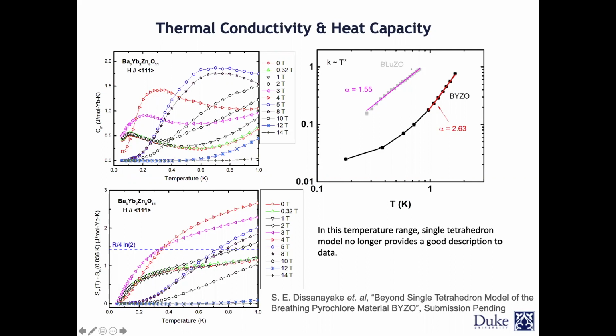And more importantly, if we start to look at the thermal conductivity, for example, this is the thermal conductivity as a function of temperature for barium lutetium zinc oxide. Lutetium is the isostructure of barium ytterbium zinc oxide. However, it is non-magnetic, so whatever it shows should be only due to phonons. And this is actually what we are seeing. If we fit it and check for K proportional to T to the power of alpha, it is more or less what you would expect if somebody only had phonons in it when you start to warm it up, and then the phonons start to show up. However, if you look at the barium ytterbium zinc oxide, you can see that down to very low temperatures, it has a different behavior and starts to saturate, which shows that something in addition to phonons is actually contributing to this.